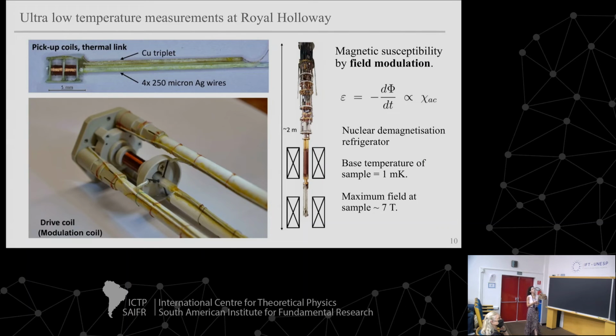Okay, so we wanted to measure lower temperature. We can measure down to about 50 millikelvin in our high magnetic fields, but not any colder than that. It's a bit difficult to do. So we had to go to some specialists. And this is the nuclear demagnetization refrigerator at Royal Holloway. And we wanted to measure magnetic susceptibility, which was a challenging thing to measure, but it's very sensitive. We wanted also to be able to measure the quantum oscillations still so that we could compare everything that we had seen above with what we would now measure below. So this took us a long time to set up, but eventually it worked.